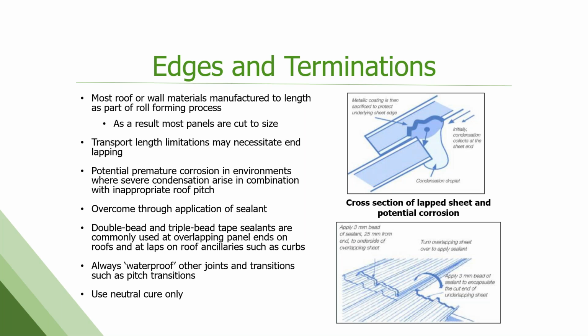So, right, if you've got an inappropriate roof pitch, which we've talked about, and a lot of condensation or moisture, that can be problematic. These inlaps, you want to use a good sealant. You always want the inlaps to run downhill so water can't go back up between those panels. Make sure you've sealed it good. Double bead and triple bead tape sealants are commonly used at these overlaps and in panel ends and at curbs. And you always want to waterproof other joints and transitions as much as possible.